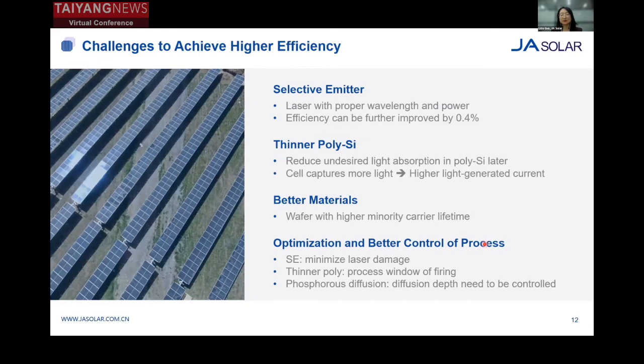Next, I'd like to talk about the challenges to achieve higher efficiency. The first one is selective emitter. The emitter region below the contact can be heavily doped to reduce the contact resistance. As we know, for PERC cell, the selective emitter is a standard process which employs the green nanosecond laser. However, TOPCon requires laser with higher energy because the solid solubility of boron in silicon is lower than that of phosphorus. So if we use the green laser, it will easily cause damage to the TOPCon cell. So it is important to find the laser with proper wavelength and power. Now, ultraviolet laser could be a good choice. With optimized SE process, the efficiency can be further improved by 0.4%.